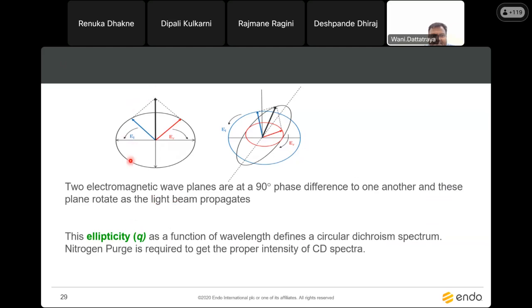Here is the ellipticity angle that I mentioned in the previous slide. In circularly polarized light, you will get some ellipticity angle. It depends on the left and right rotation by our molecule. When they are equal, it will nullify and will not show any ellipticity angle. So circularly polarized light will be absorbed differently in the different directions and will give some ellipticity angle. We have to calculate and measure that ellipticity angle.